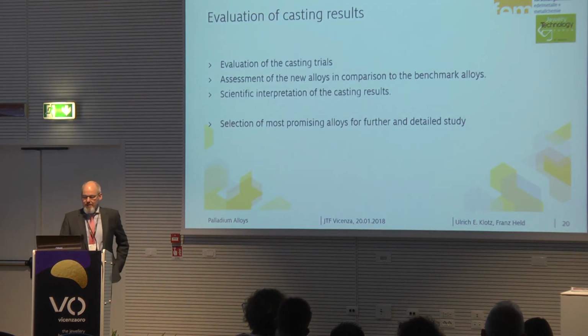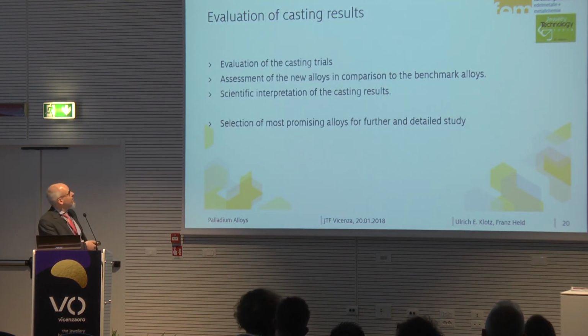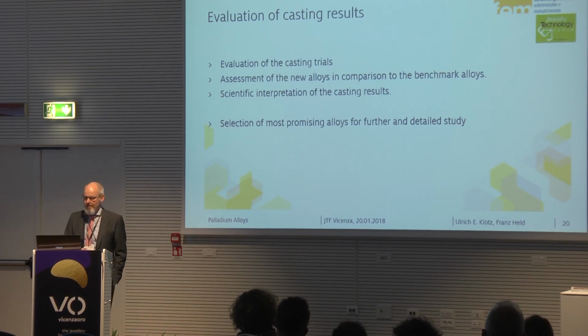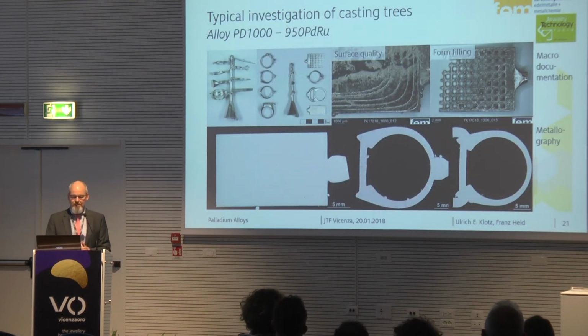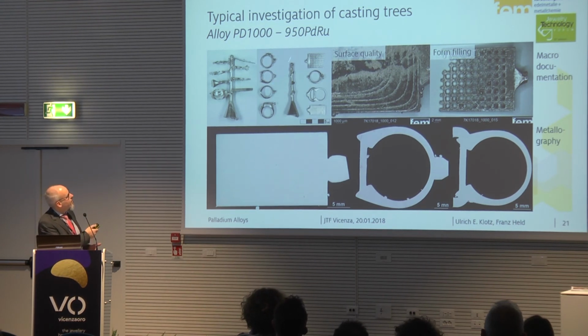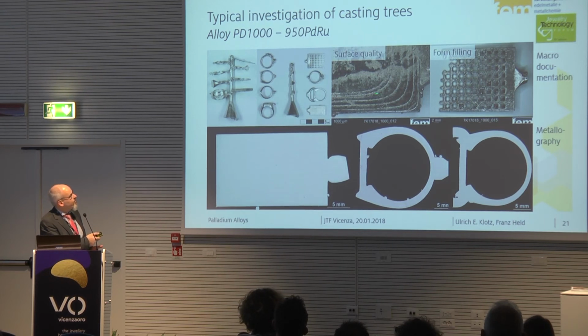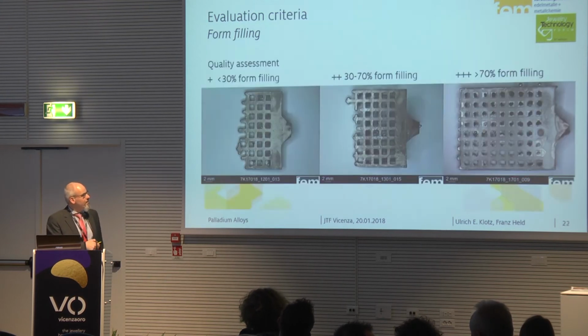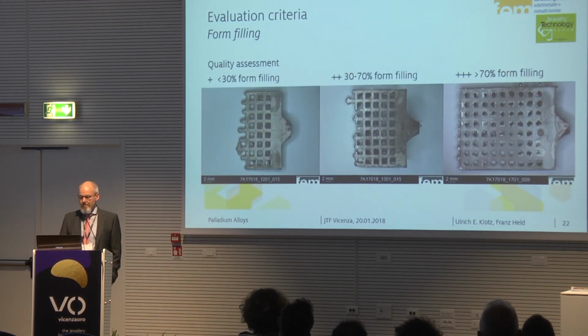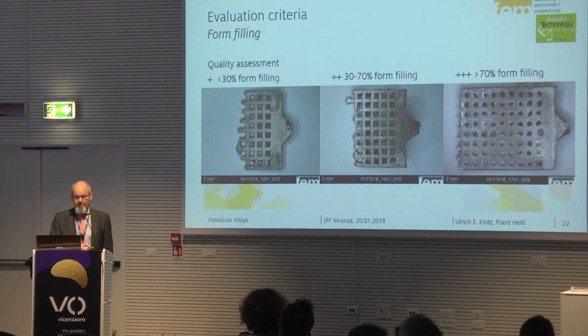Well, the casting result. We assessed several new alloys, interpreted the results, and we did it in a way like this. So this is a typical casting result, the tree after casting, parts cut from the tree. We get the surface quality, form filling, and metallography. And now we found different cases.